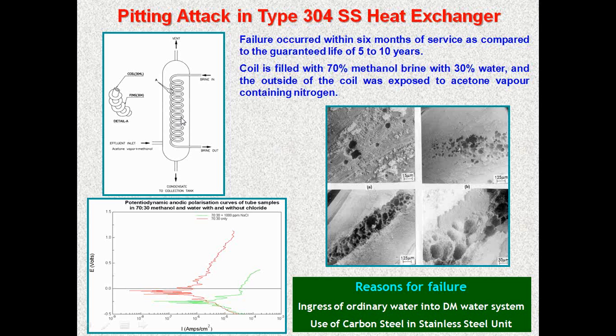The investigation found that when you have only chloride, such pitting attack will be very significant. And the study showed that sometimes ordinary water was used to prepare the chemicals, and this ordinary water contained more chloride, which led to the pitting. Instead of DM water, which was not available for a short time, ordinary water was used, and that contained a large amount of chloride ion that led to the pitting attack.